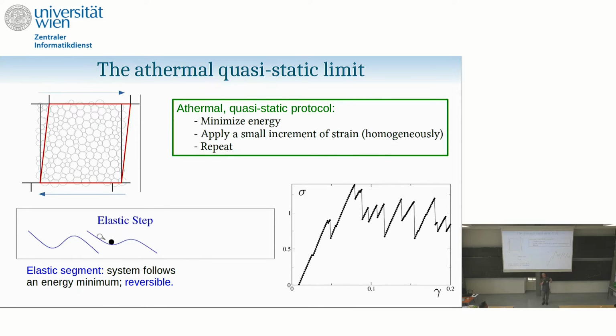When I strain my system, I change the potential energy surface, and I change continuously the basin, the structure of the potential energy surface. Okay? So I can go in a direction, and if I have, for example, not periodic boundary conditions, but walls, this parameter just encodes the positions of the wall. You could imagine that you are confining your system by walls. The potential energy that you consider is the potential energy of your atoms and of this system with the confining walls. And the parameter here is the relative position of the walls. So you can do this in a general case.